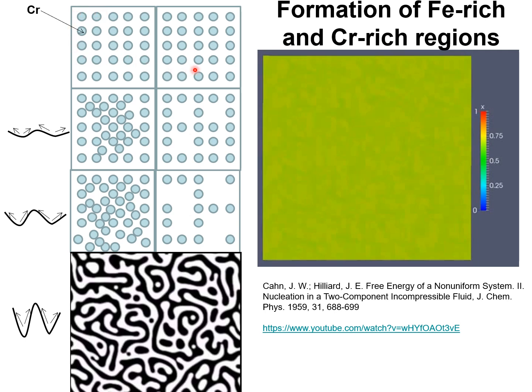Following up from the previous slide, let us take a system consisting of iron chromium at a composition of 0.5 in the unstable region. I draw only the chromium atoms here. Initially, the compositions are uniform in two regions, say within the unstable region. We subject the system to a small perturbation which leads to a higher amount of chromium in the left compartment than in the right compartment.